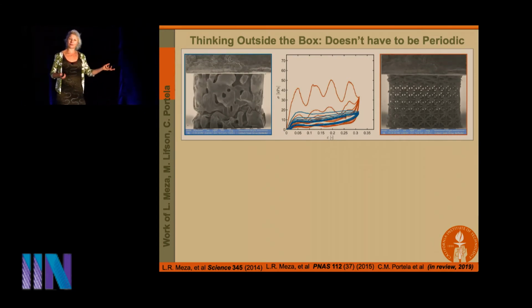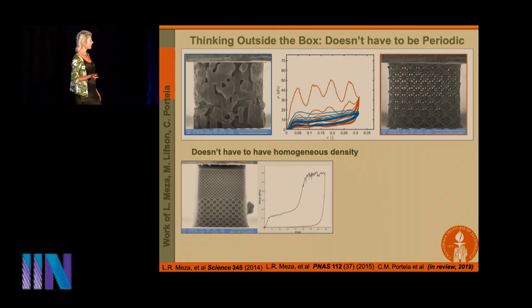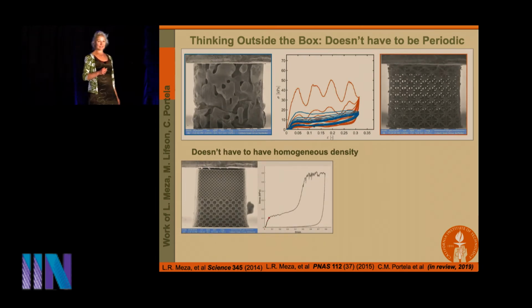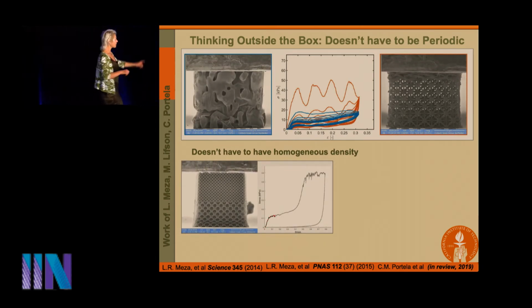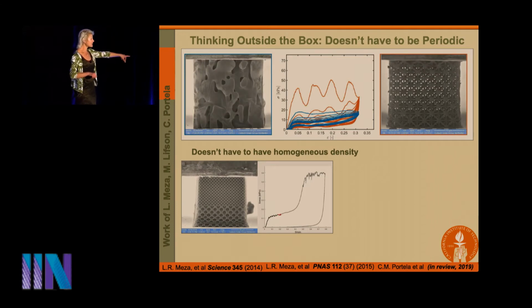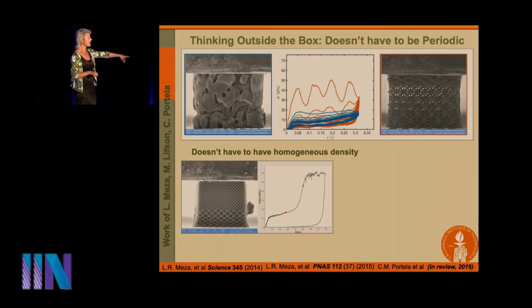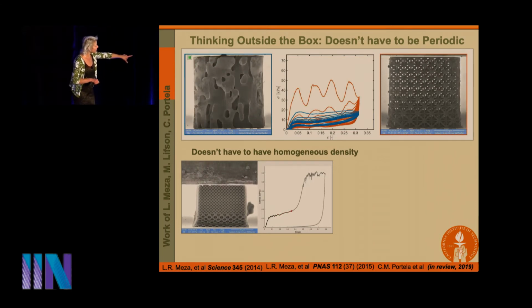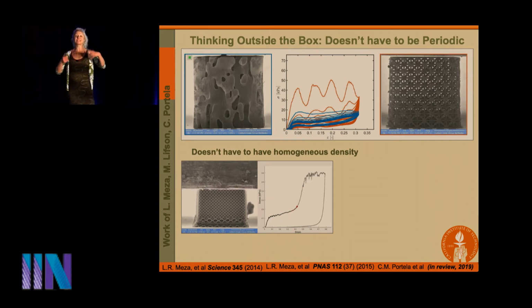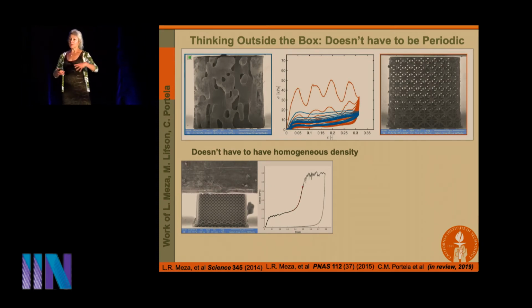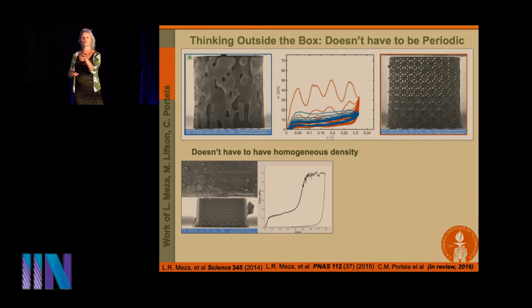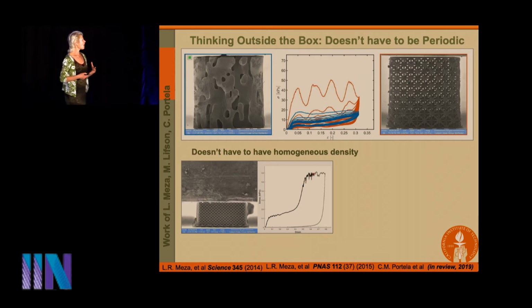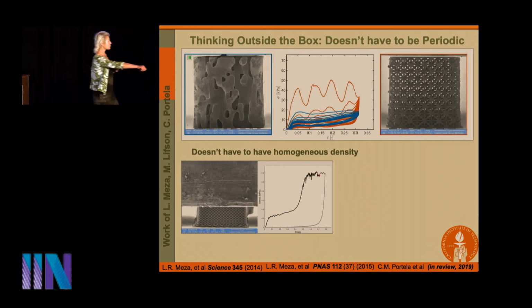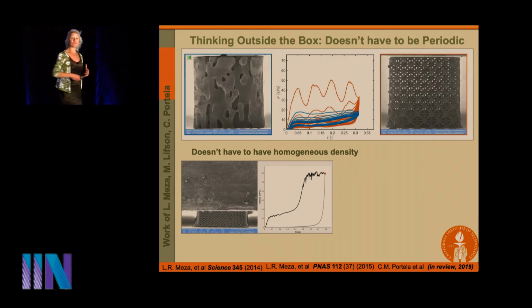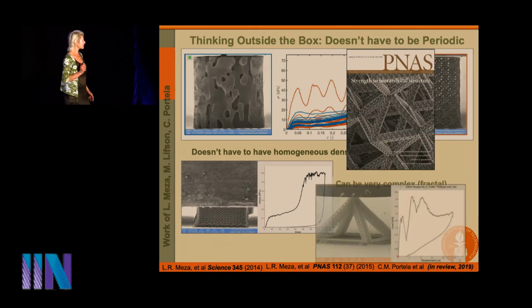So complex architectures, complex stress states, not periodic. You can see that the density doesn't have to be homogeneous. And what I'm showing you here is a material that has two different density regimes. So this is, of course, lower density, higher density. And at this point of compression, this part of the sample doesn't even know that it's being compressed. So you can pre-build trajectories of deformation and trajectories of how the stress and the strain are going to respond at different strain rates. So that gives you that flexibility.